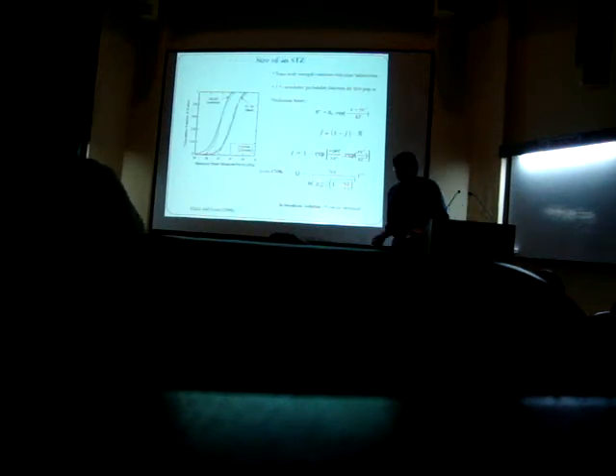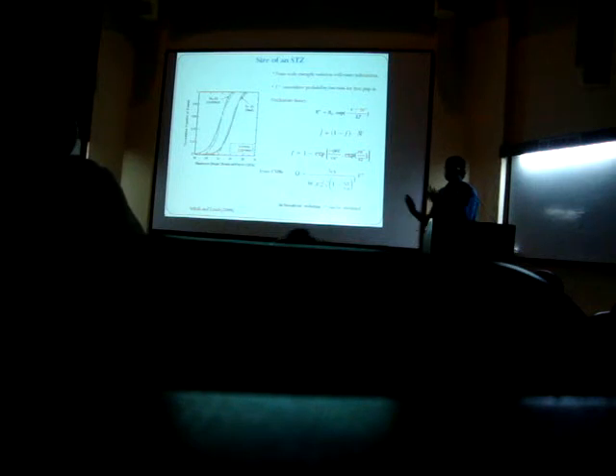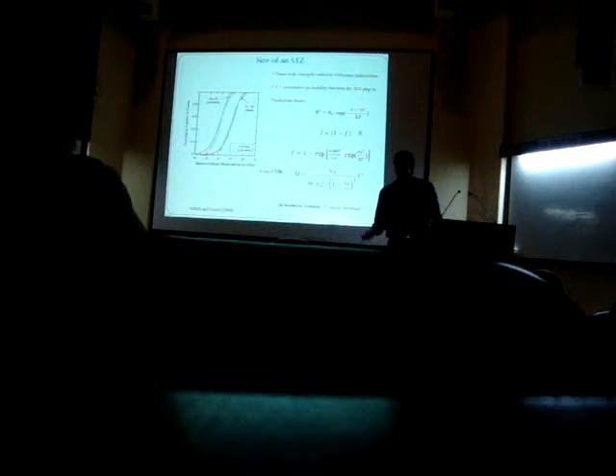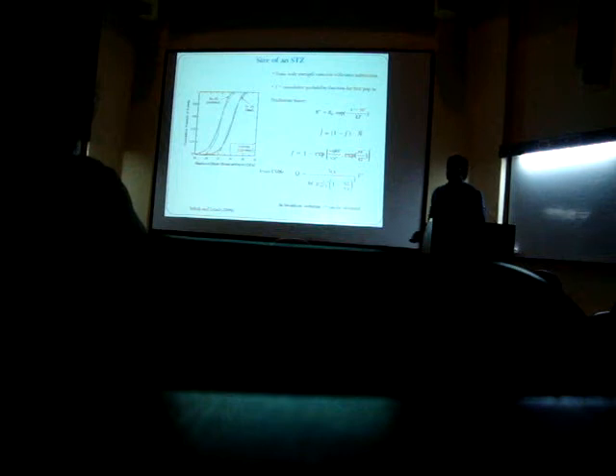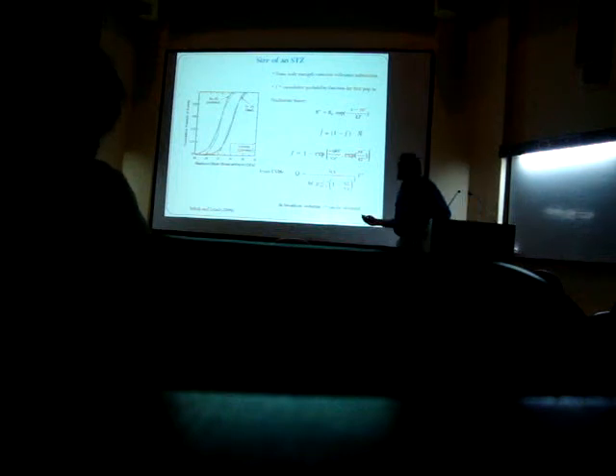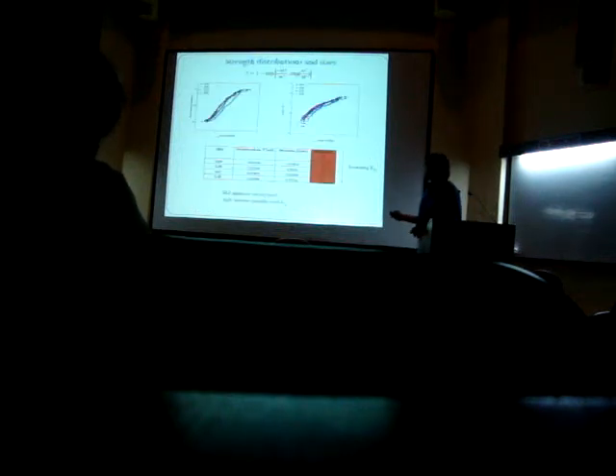So we keep three things in mind. One is number of shear bands increases because of higher temperature, and the density is also changing, which means higher free volume. The third thing is we want to consider the size of the STZ. So we are moving to the atomistic aspects now, and we saw that using the nucleation rate theory developed by Schuh, we were able to determine the following numbers. The number of atoms in an STZ for all the cases are almost similar.